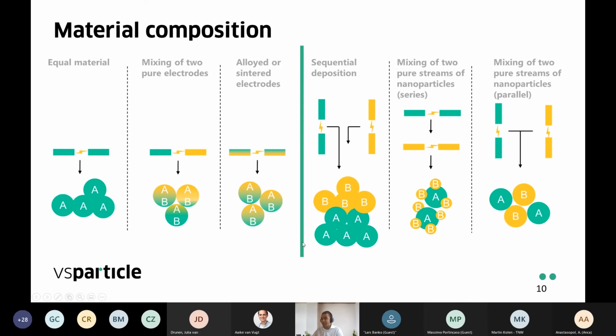On the right of the solid green line, I show you what happens if we have multiple spark generators. And here it really depends on what the order or sequence configuration of these spark generators is, and that will then determine what your materials are. So if you have sequential deposition, you can really form layered materials. If you have your nanoparticle generators in series, you can form core shell type structures. And if you mix the two streams in parallel, you can again form some form of mixed alloy phase.